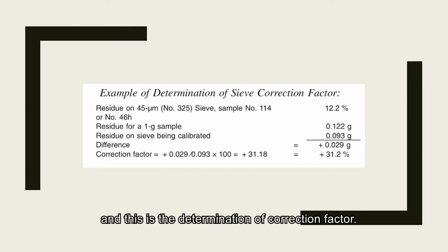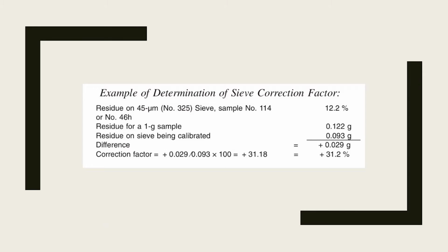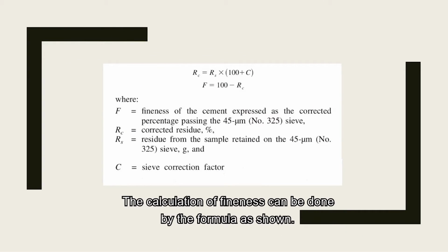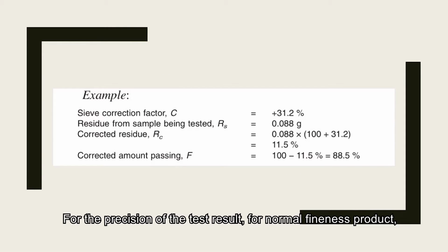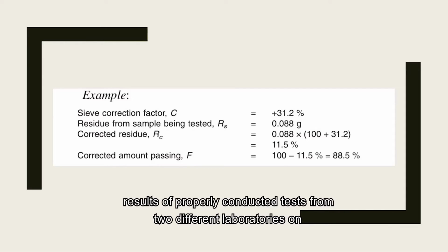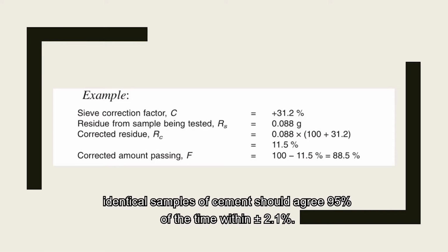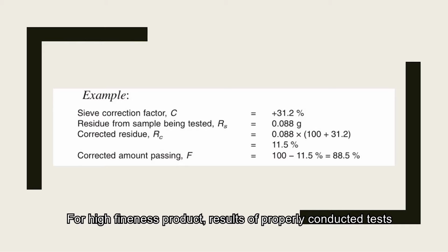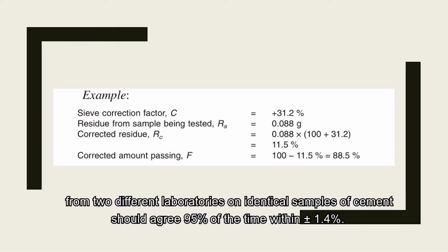And this is the determination of the correction factor. The calculation of fineness can be done by the formula as shown. From the precision of the test result for normal fineness products, results of properly conducted tests from two different laboratories on identical samples of cement should agree 95% of the time within plus or minus 2.1%. For high fineness products, results of properly conducted tests from two different laboratories on identical samples of cement should agree 95% of the time within plus or minus 1.4%.